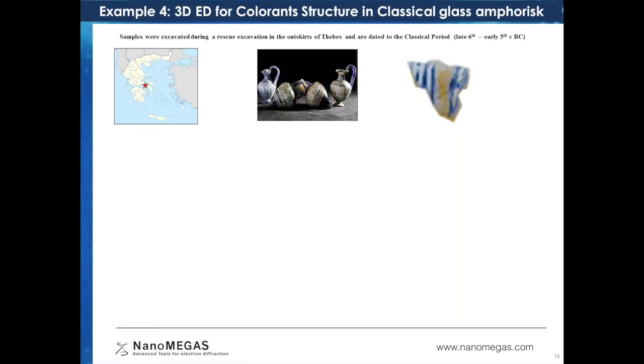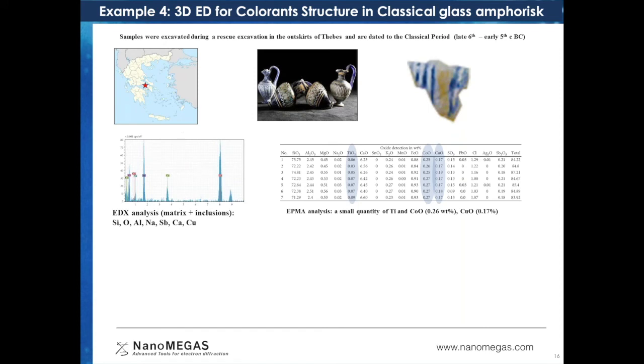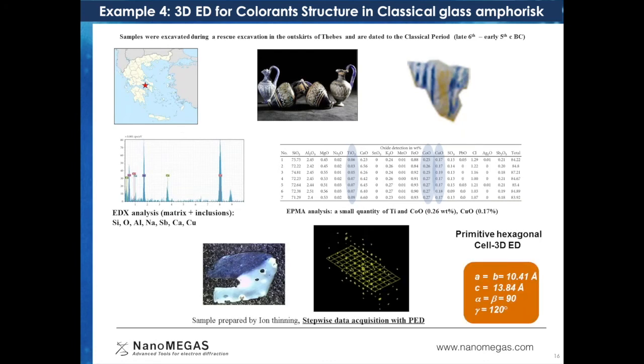First, we did EDX and EPMA analysis to find the chemical composition of the pigment. In the chemical analysis, we observed the natural composition of silica, that means a lot of silicon oxide, but we also observed traces of titanium oxide, cobalt oxide, and copper oxide. Then we prepared samples for the TEM experiment by ion thinning, and collected 3D electron diffraction data in stepwise and precession mode. From the 3D electron diffraction data, we got a primitive hexagonal cell.